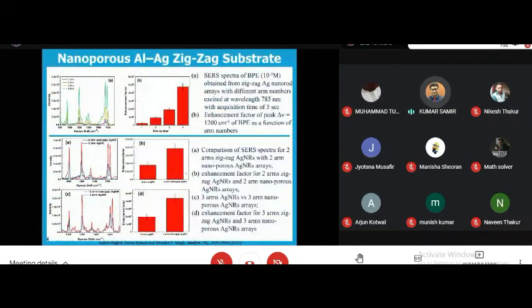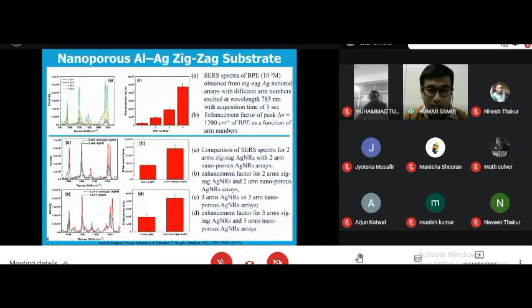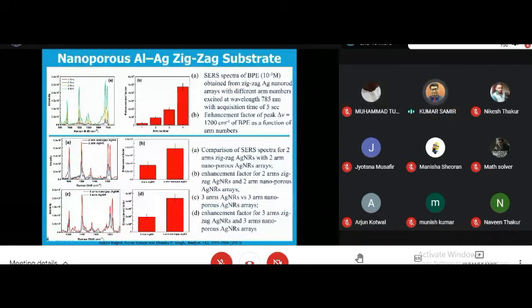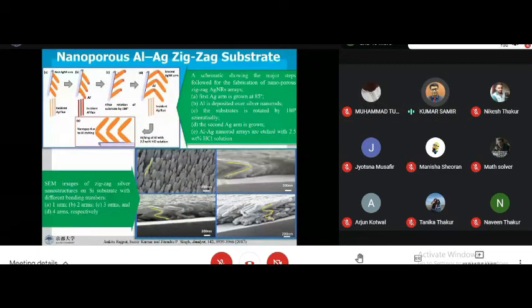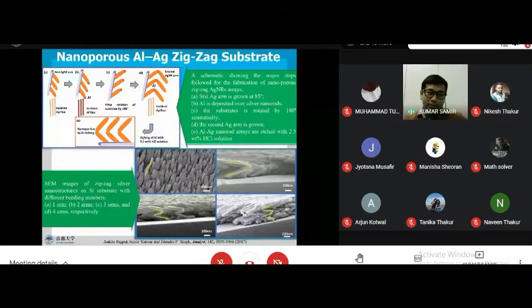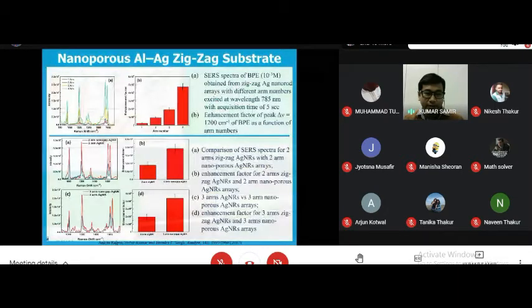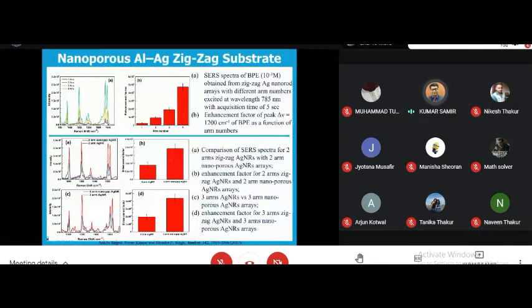By doing this, what we found is that for the pure silver nanostructure, the SERS enhancement increases with the arm number. So you are going in the third dimension, increasing the hotspots in the third dimension without taking much space on the substrate. And for the second structure, after depositing the aluminium, we also etched out the aluminium later using HCl to form nano gaps in the arms, and that further increases the SERS signal. For two arm it is like double, and also for three arm the signal doubles. So by creating the nano gaps, we can further improve the SERS signal.